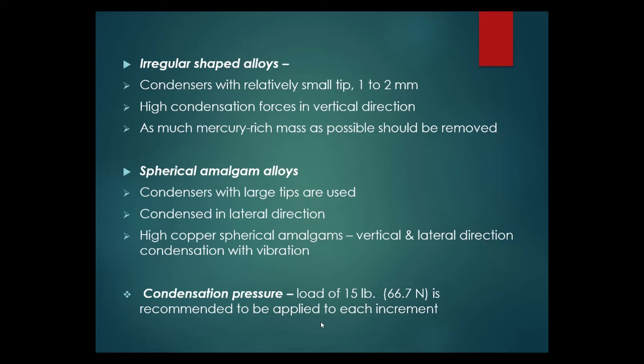For spherical amalgam alloys, condensers with large tips are used and condensation is in the lateral direction. For high-copper spherical amalgams, condensation is in both vertical and lateral directions with vibration. Condensation pressure required is a load of 15 lb, equal to 66.7 N, recommended to be applied to each increment condensed.